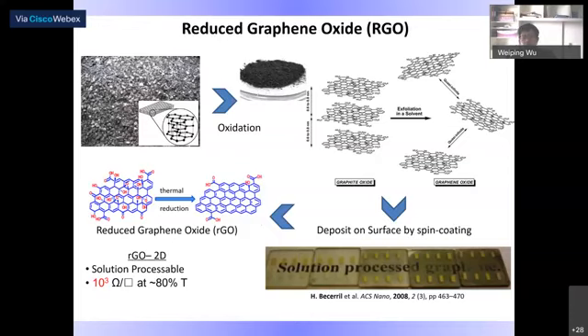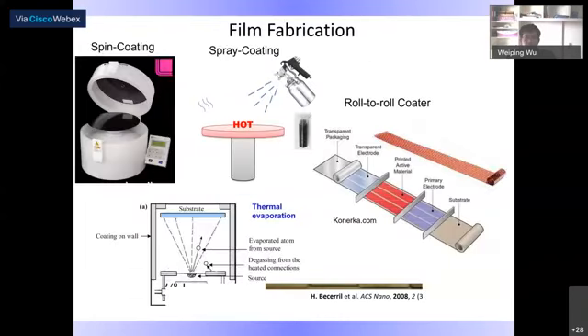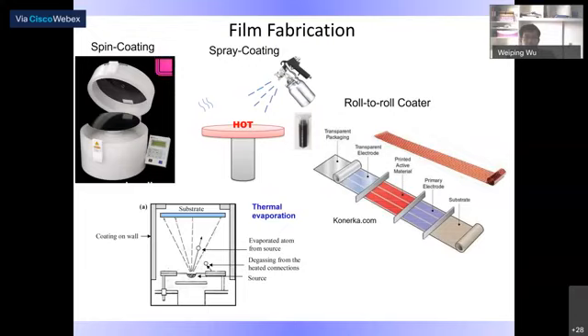So we actually could not get a very high, excellent performance from graphene thin film. The sheet resistance is about 1 kilo or a few kilo ohms per square, with 70%, 80% transparency. Then there are other thin film fabrication methods like spin coating, spray coating, roll coating, and so on. You have advantages over thermal evaporation in low cost and large area.